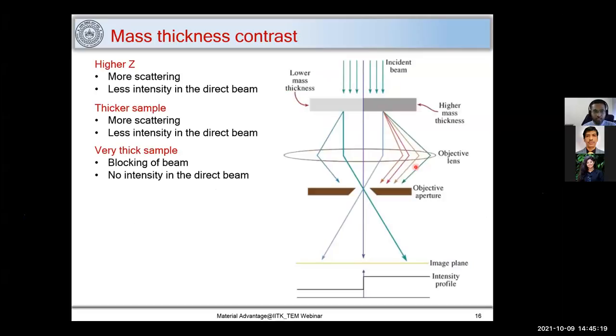Now coming to mass thickness contrast. So we have seen this. Consider this image, and here you have lower mass thickness. So thickness is lower, so it will not scatter rays as much as this region is scattering. And that is why you will have maximum intensity at the image plane. Whereas here the electrons are being scattered more, so it loses intensity in transmission mode, and thus you have lower intensities here.